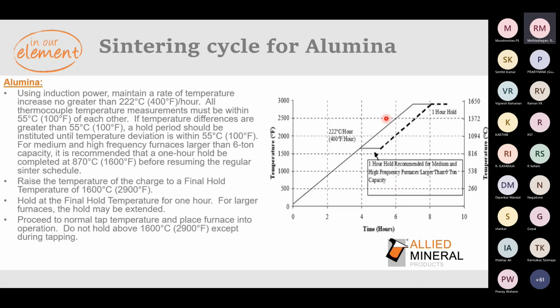That cycle is normally used for silica linings. But for alumina linings, for steel melting applications, we suggest going between 200 to 220 degrees Celsius per hour, and then you can directly shoot up to 1600 degrees Celsius and hold. In the case of larger capacity crucibles, you can hold at around 870 or 900 degrees Celsius for 1 hour.